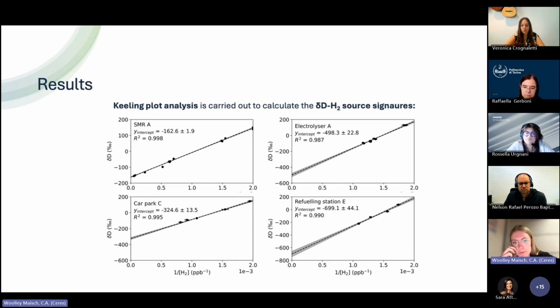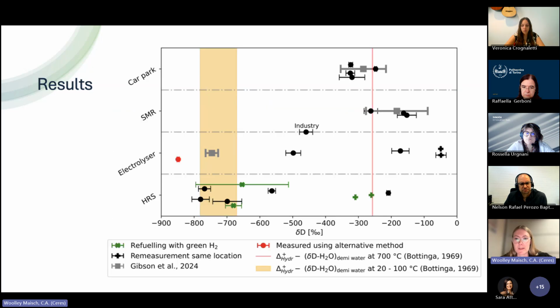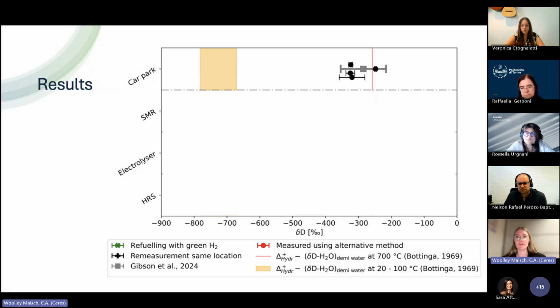So here's some examples. This is one SMR we visited, and we took a lot of different samples, we plot them, we have a nice R squared, and then we get the source signature. And we do the same for the electrolyzers, and then basically we have this big results figure, and there's a lot going on here, so I'll go through it one at a time. Firstly, there's a decent amount of literature, relative to how much literature there is on this, for combustion sources.